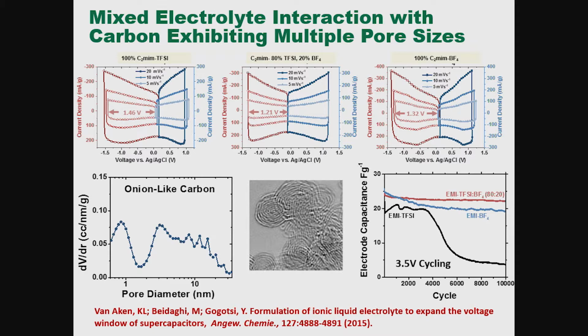The advantage there is that neither electrode experiences an extreme potential. The net result is a much improved cycle life of this electrolyte, even at a 3.5 volt cycling window, compared to, for instance, the pure EMI-TFSI, which degrades after about 5,000 cycles.